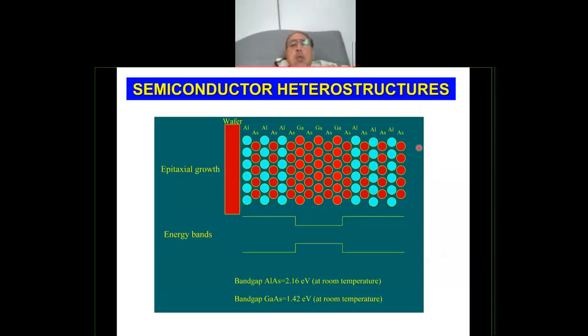Okay, so how can we make semiconductor heterostructures, as the patent tells us? So the patent says, heterostructures are practically just like a sandwich structure. You just put different semiconductors one on top of the other. This is just like sandwich structures. So here, for example, you can see I'm just using some elements from group 3 and some elements from group 5. So aluminum, arsenic, and they build them layer by layer. And then you have here gallium arsenide, and then I top it up with aluminum arsenide. These are just layer by layer, atom by atom on the surface.